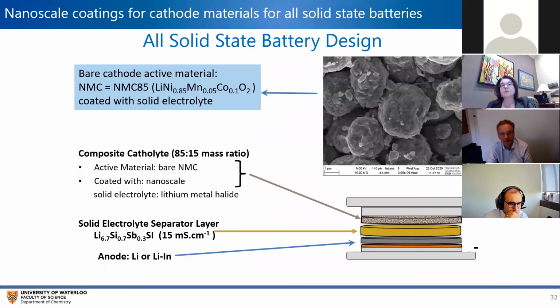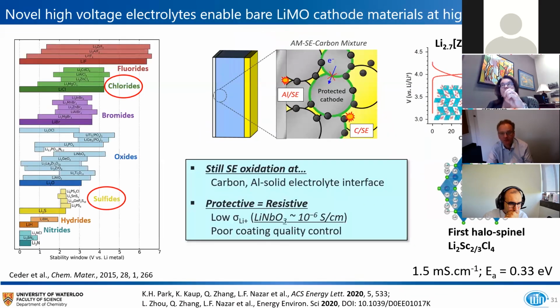Now, the round trip efficiency is kind of the polarization of the cell, and it's completely dependent on those interfacial reactions at both the positive and the negative electrode, and defines the voltage difference between the charge and the discharge.